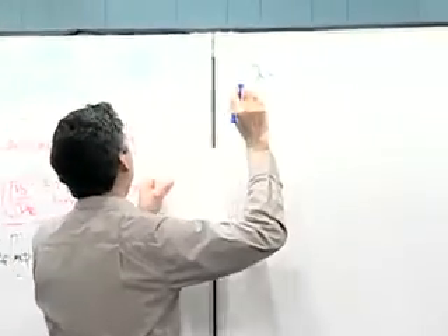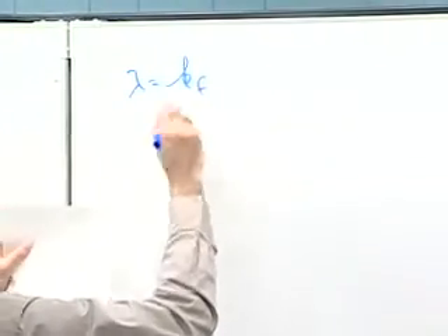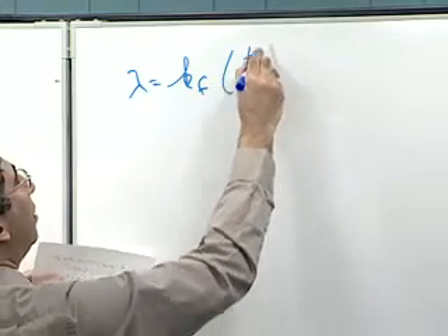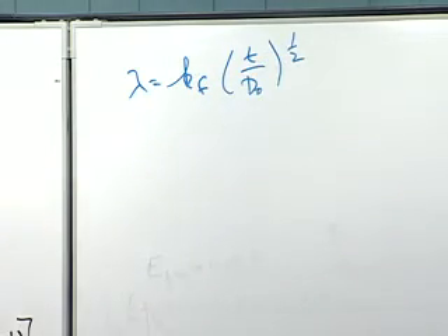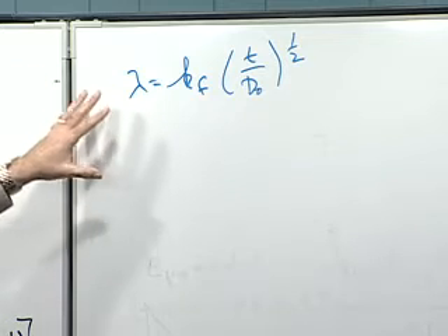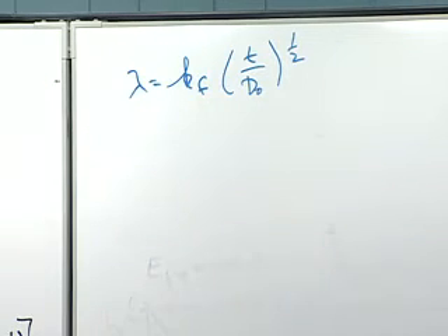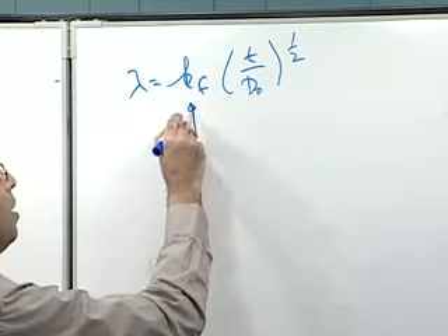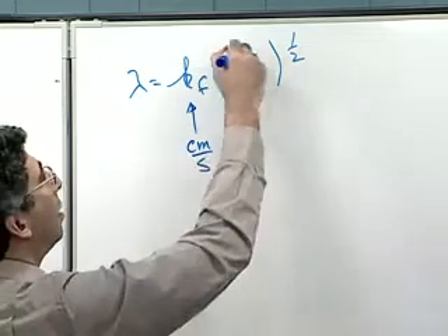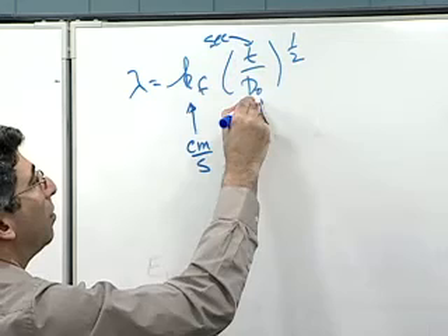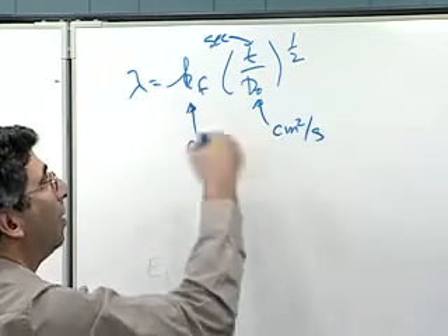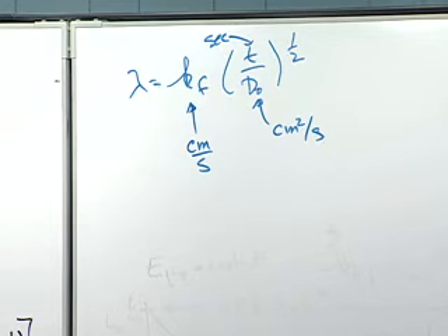And to get there, all we do is we define a new parameter that's going to bunch a lot of these terms together, lambda equals k_f t to the 1/2 over D_0 to the 1/2. Now, why do I do that? You'll notice what I've done in doing this is I've taken parameters that have certain dimensionality to them and removed the dimensionality. That is, I've gotten rid of the units. Because k forward is going to have units of centimeters per second, you'll recall. Time would have units of seconds. And our diffusion coefficient, centimeters squared per second. And so when I multiply all that together, I now have a lambda that is unitless. Okay, so I've put all my time parameters, if you will, together and made a unitless parameter.